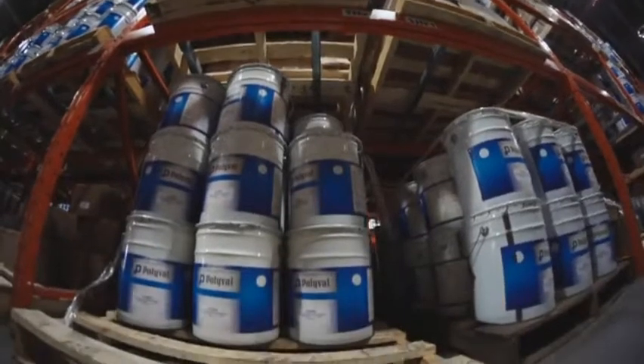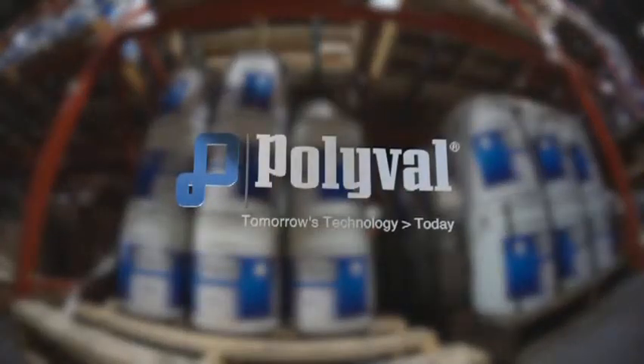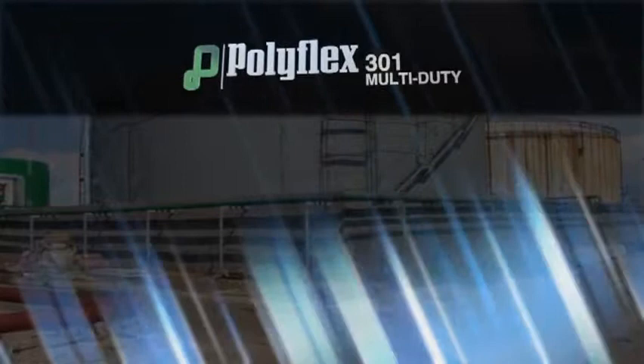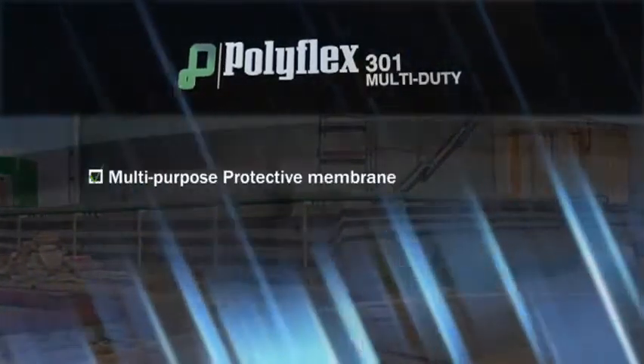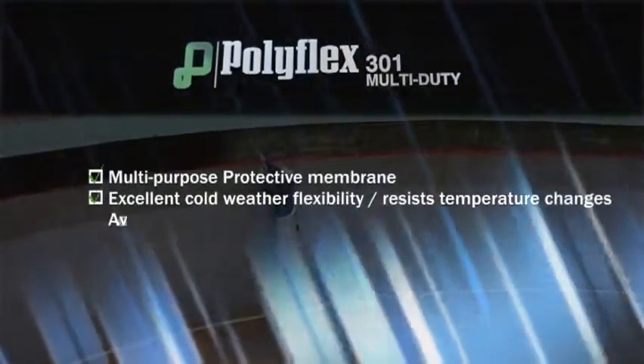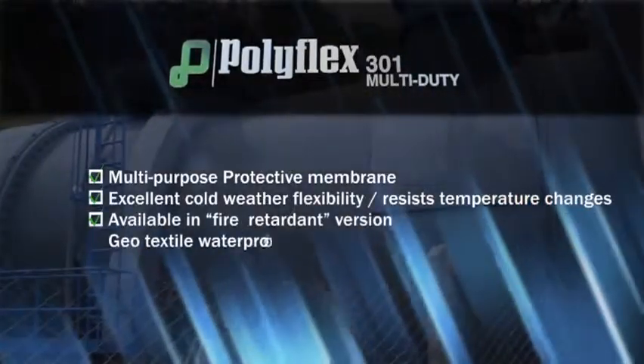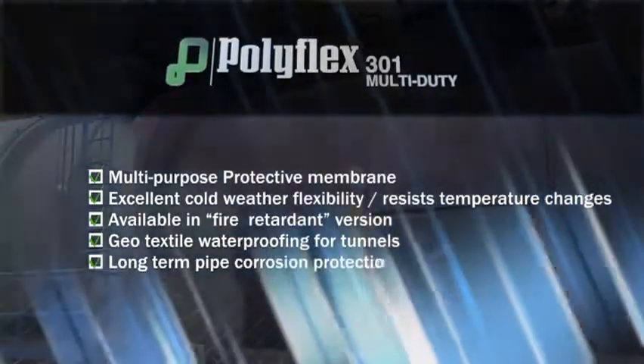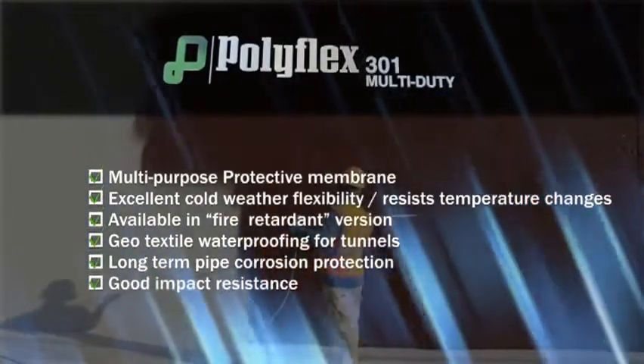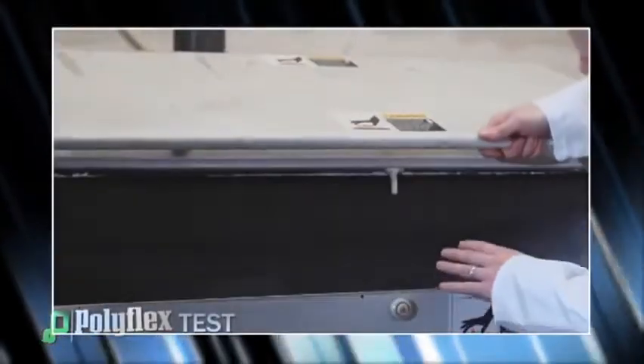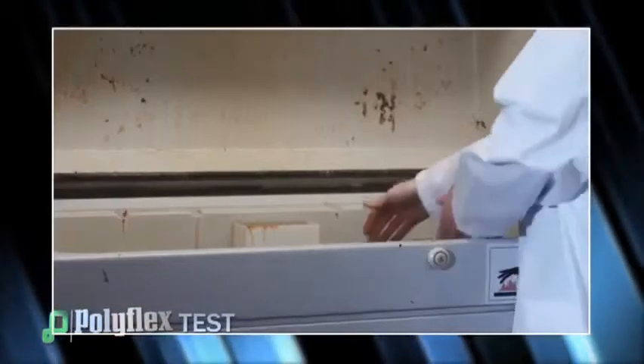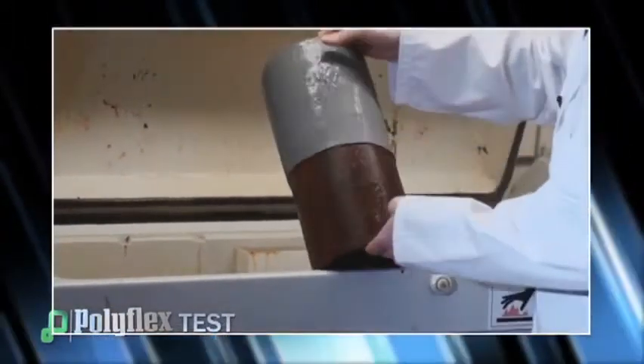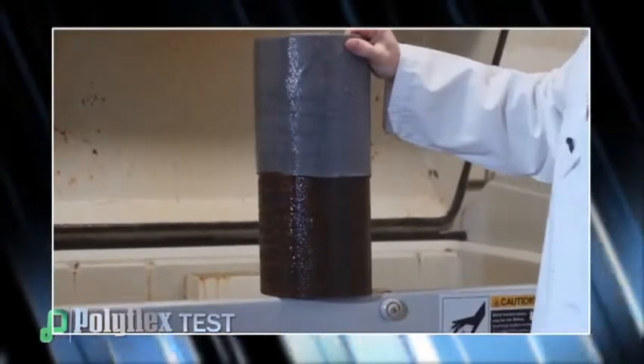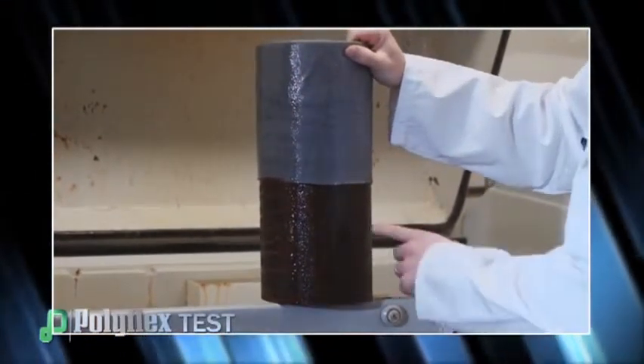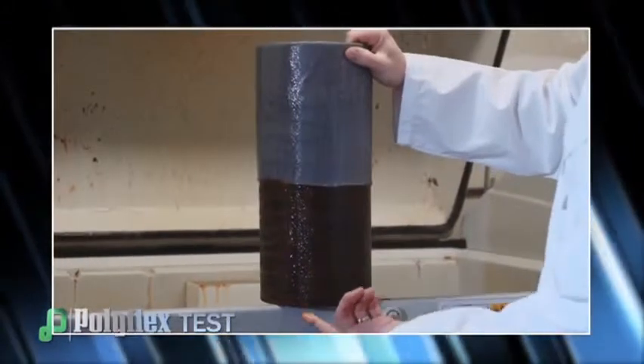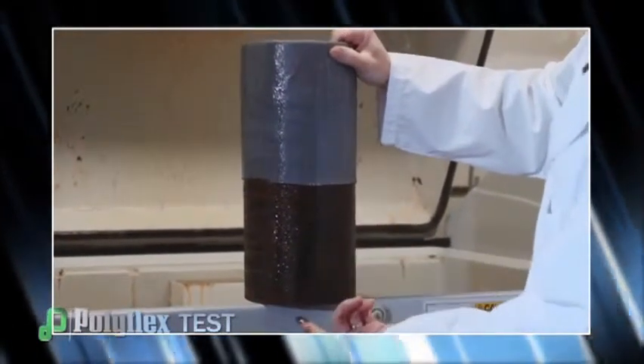Here are a sample of some of the coating systems available from Polyval. Polyflex 301 Multi-Duty. Here is an example of a corrosion test involving salt spray that accelerates the corrosion effects of a pipe test substrate, as per the ASTM standard testing method. Here we see, via the acceleration test, the equivalent of many years of corrosion.